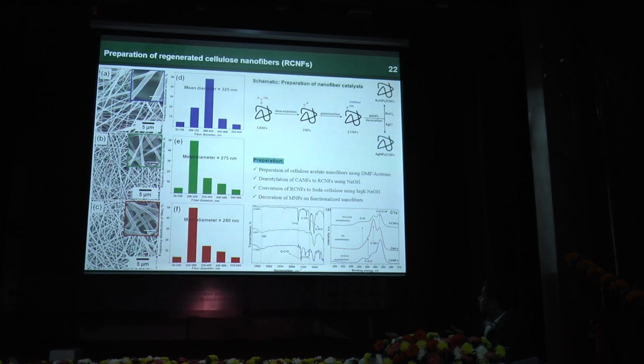So this is the experimental procedure. I can briefly explain this. We electrospin cellulose acetate nanofiber, then we deacetylate it into cellulose nanofiber. In fact, cellulose acetate stability is not that good, so we converted it into cellulose form. Then we modified the surface to bring the positive, negative charge, and then we coated nanoparticles on the nanofiber. So the thing is, when you go for chemical modification, you should maintain the morphology of the nanofiber. So you can see even after modifications, the fiber morphology is intact.